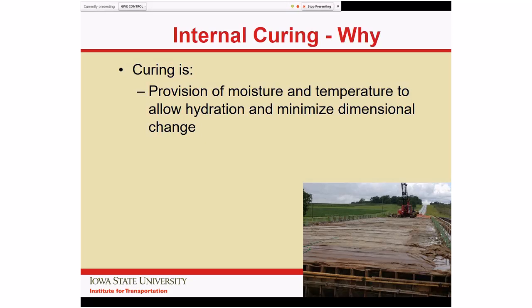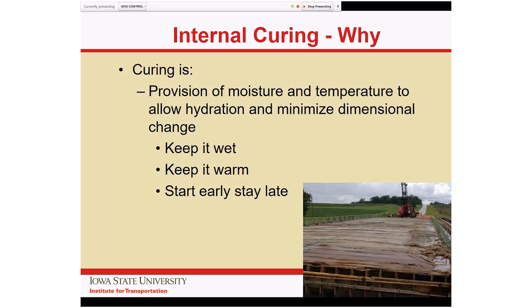We also want to keep it warm. If it gets too cold, the reaction will slow down. If it gets too hot, some interesting things may happen. So, the basic rule about curing is keep it wet, keep it warm for as long as you need. And typically for the sort of mixtures we're dealing with here, we're probably looking at 3 to 7 days of protecting the concrete from the environment.